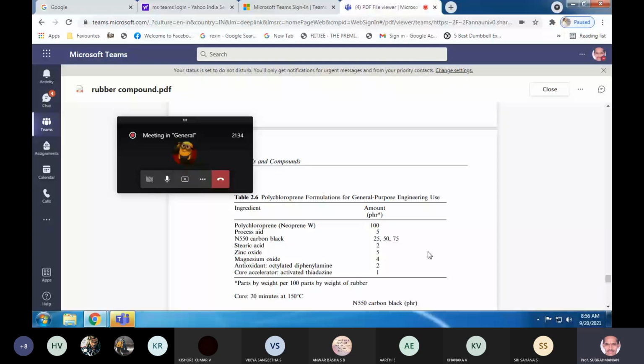In fact, EPDM we continue to use in very large quantity just because of its low specific gravity, about 0.82 to 0.84. Whereas chloroprene rubber specific gravity is 1.23. What does it mean? For a given volume, the product mass would be higher. All right, and so that may limit filler addition.